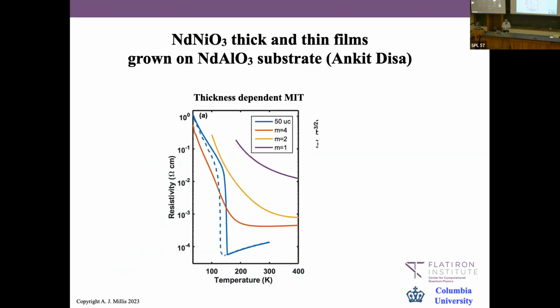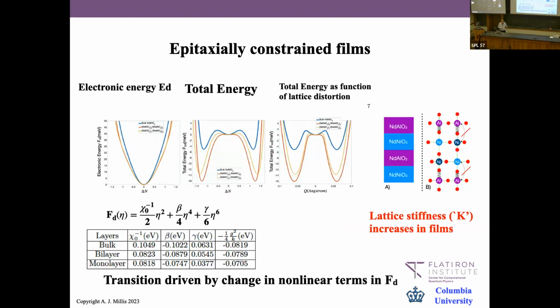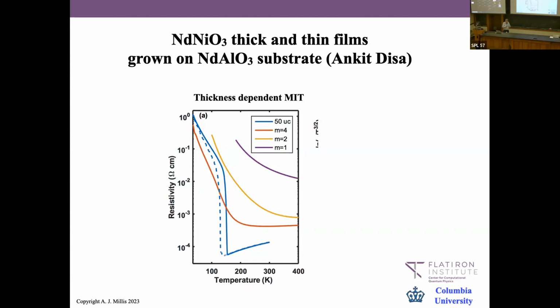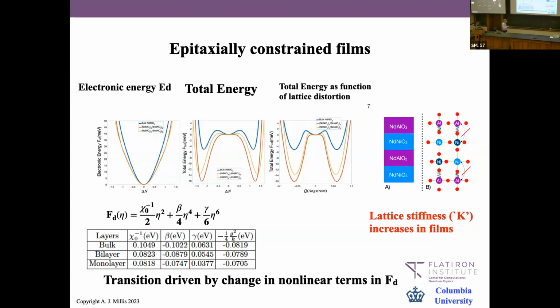Okay, you can play the same game with films. Since we're running late, I probably won't do that, except to say that interestingly, you can understand these results on the film thickness dependence in a rather peculiar way. This is bulk and two films. What you see is that the quadratic terms around the minimum are almost the same for all the cases, even though the metal-insulator transitions are quite different. And the thing which is changing is the nonlinearities, right?